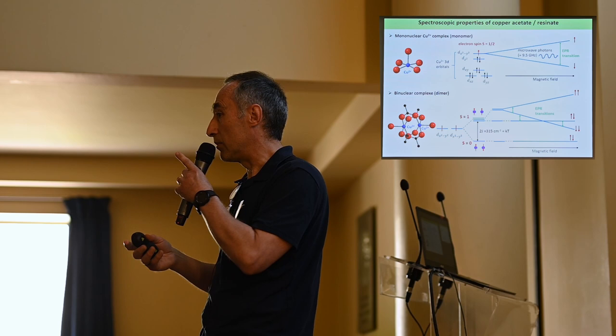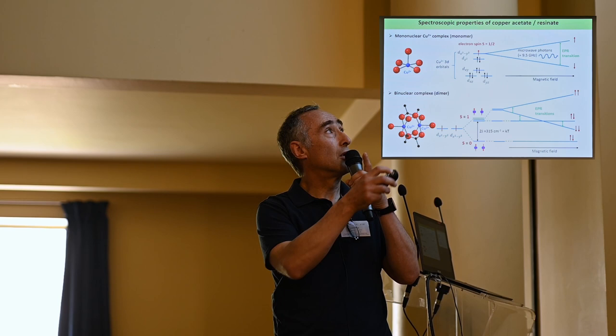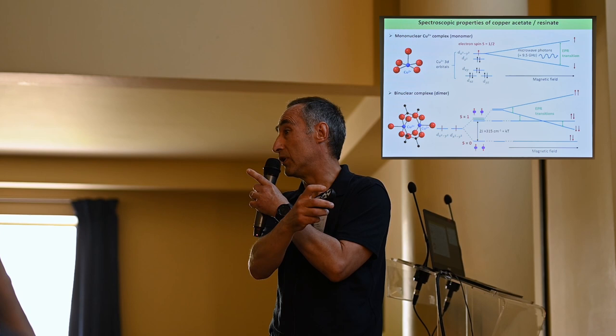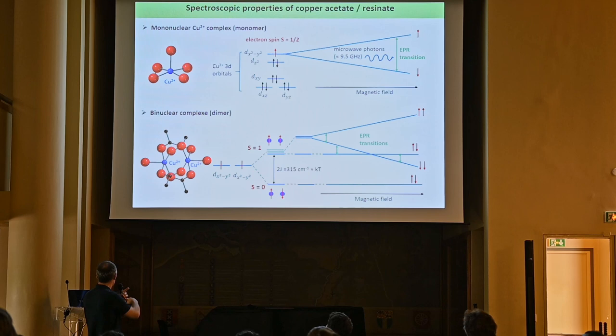Because the exchange splitting is comparable to thermal energy at room temperature, about 10 to 20 percent of the binuclear complexes occupy this excited state at room temperature, so you can observe an EPR spectrum for the binuclear complex.